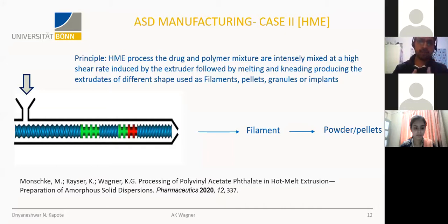So the drug and the polymer mixture are intensely mixed at a high shear rate, because in hot melt extrusion we have a barrel, which is the black line, and we are heating it. So the melting and the kneading takes place inside the barrel, and it is conveyed via screws. We have conveying blocks here, and this green stands for the kneading blocks, where the kneading angles are set at like 30, 60, or 90 or 0 degrees. So we can modulate that in order to obtain the right amount of shear rate. And it's also a trial and error experiment, and also it's based on experience of extrusion, where you can achieve higher shear rate, but you also have to take into account that you don't degrade your product.